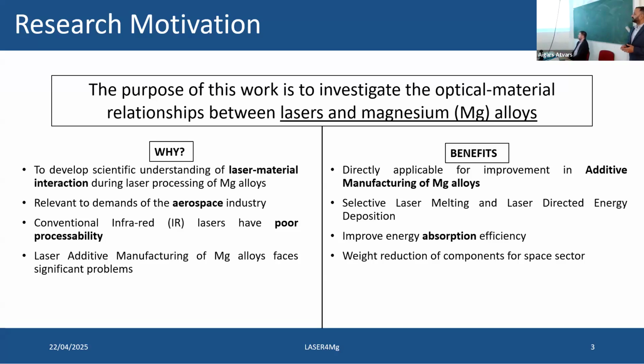I will speak about why, but to highlight the reason: the conventional infrared lasers, which are industrially used for processing of metals, have poor processability with magnesium alloys. Specifically because the reflection of laser light by magnesium alloys is very high and the absorption is very low, due to which we have to figure out ways to find a laser system that works best with magnesium alloys. Due to this problem, laser-based additive manufacturing of magnesium alloy currently faces significant problems. However, we see that titanium alloys, steels, and even aluminum alloys are being successfully 3D printed with lasers.